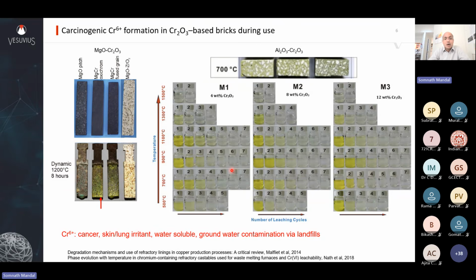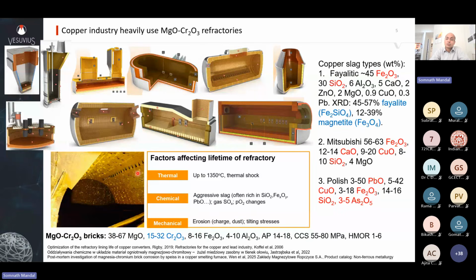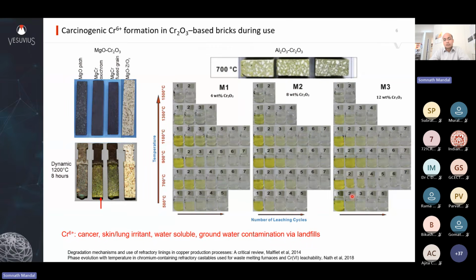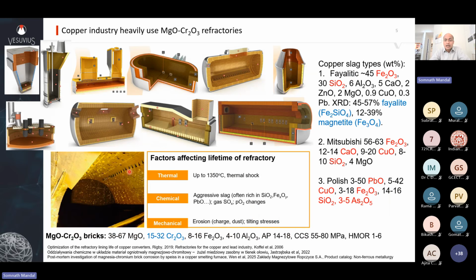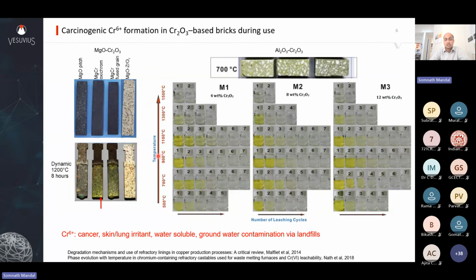So, very good. Chrome refractories are great. However, during service, especially in contact with calcia and sometimes soda, they change. Soda is added in some of the copper furnaces to take out arsenic from the material. The arsenic vaporizes in the presence of soda. So arsenic removal is helped by soda, but soda and calcia, these two guys, convert a big chunk of the trivalent safe chrome variety to hexavalent chromium. And then this Cr6+ is carcinogenic. It causes cancer. And people involved in dismantling used refractories and then disposal of them are exposed to dust that is carcinogenic. They also cause skin and lung irritation.